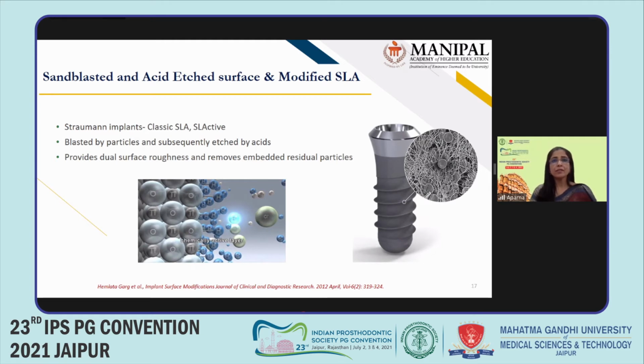So you have a surface which is first sandblasted and then acid etched. So what does the etching do? When you have sandblasted, I told you initially that it creates a very roughened area. You have peaks and you have pits. So when you're etching the already sandblasted area, it tends to tone down the heights of the peaks which are created by sandblasting, and it also creates smaller pits. So basically, the average surface area is reduced.